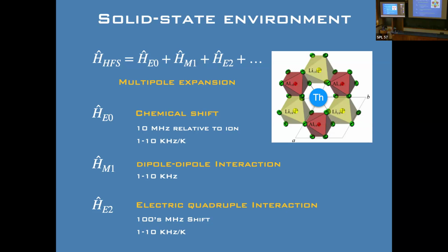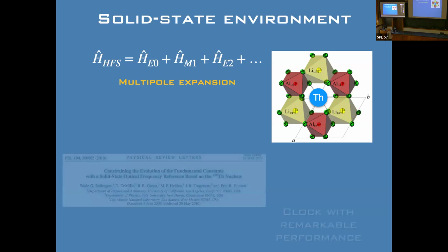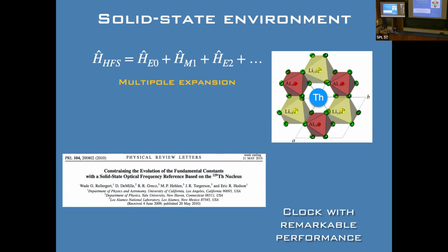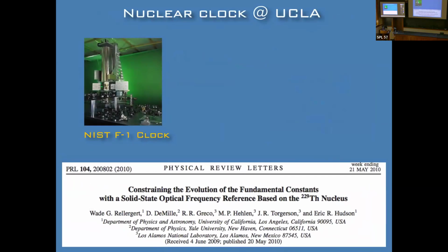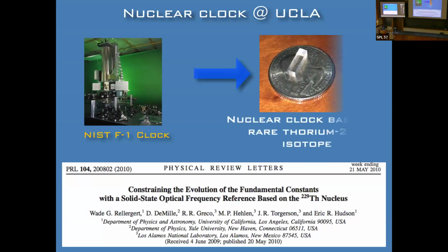I hardly ever show this slide, but I'm going to show something new at the end of the talk, and I wanted to set this up. What that led us to do was say, hey, you could actually dope thorium-229 into these crystals. And because you can put so many thorium in, 10 to the 17, 10 to the 18, 10 to the 19, the signal to noise ratio leads to a clock with what I would broadly call remarkable performance, stabilities that you really can't access any other way. Now, the thing that paid the bills was to take the time that defines a second for the nation and replace it with just a crystal. That's how we paid the bills, but it's not really the genesis of this idea.